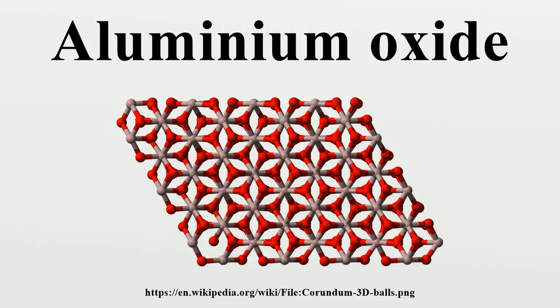Aluminium oxide is responsible for the resistance of metallic aluminium to weathering. This layer protects the metal from further oxidation. The thickness and properties of this oxide layer can be enhanced using a process called anodizing. A number of alloys, such as aluminium bronzes, exploit this property by including a proportion of aluminium in the alloy to enhance corrosion resistance. The aluminium oxide generated by anodizing is typically amorphous, but discharge-assisted oxidation processes such as plasma electrolytic oxidation result in a significant proportion of crystalline aluminium oxide in the coating, enhancing its hardness.